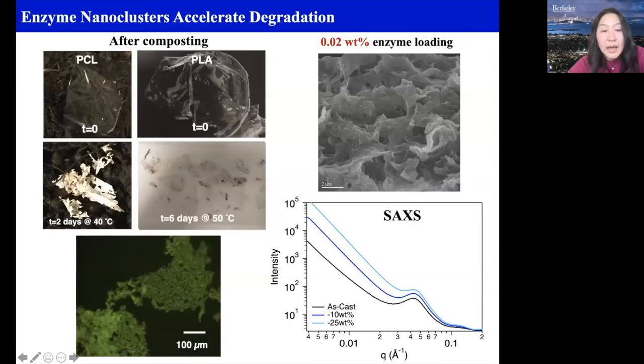And we also want to see what happened to the microplastic after the plastic got disintegrated. As long as you get the material to degrade, you cannot avoid microplastic formation, unfortunately. So the key is to make sure that the microplastic can continue the degradation process. In this case, what you see is that even though the microplastic still forms inside, there's still enzyme embedded, and that explains why we can get a near complete degradation.